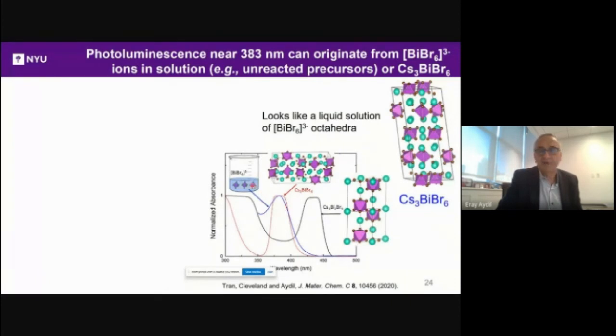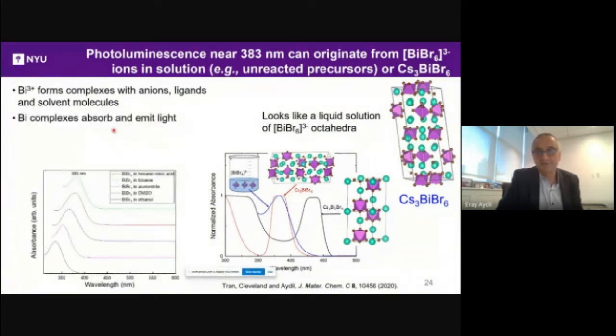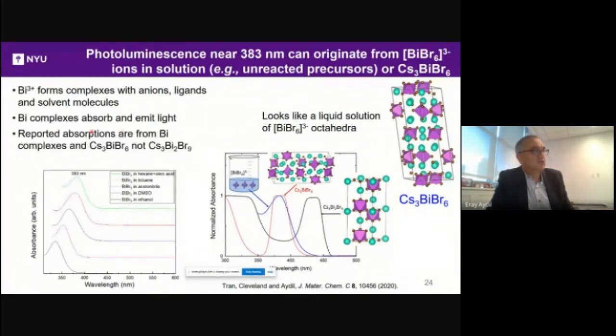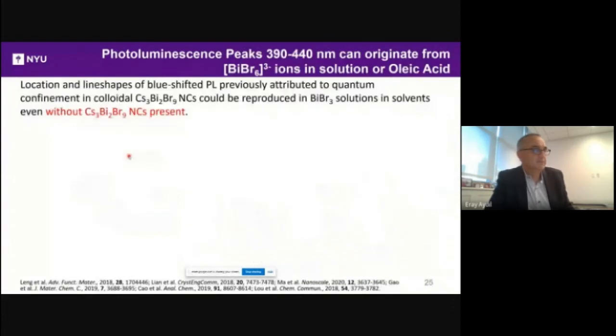However, if you were to make it with liquid, there could be contamination, and it could shift depending on the solvents, because that Bi3+ is forming complexes with anions and ligands and solvent molecules, and it can fool you into thinking that that's coming from the solid. So we think that the reported absorptions are not from the Cs3Bi2Br9, but from bismuth complexes, or possibly from impure Cs3Bi2Br9 with some Cs3BiBr6 material in it.